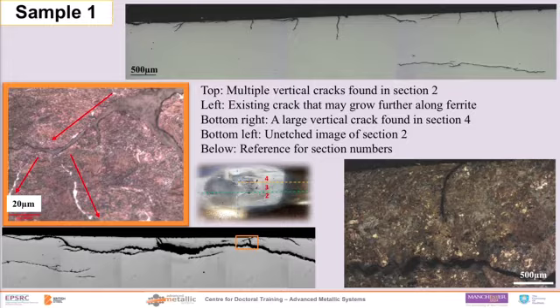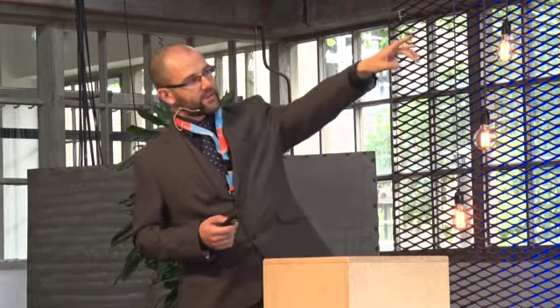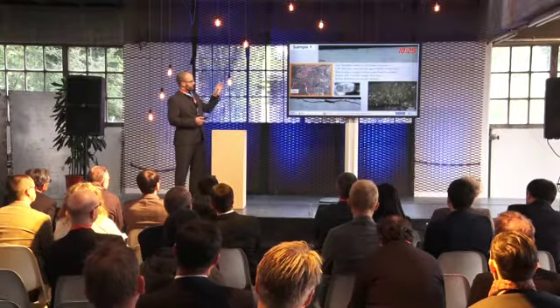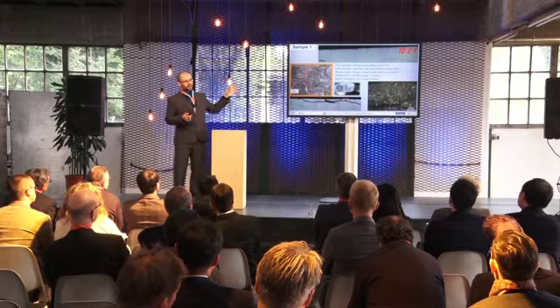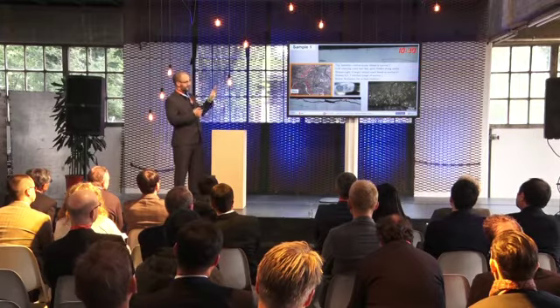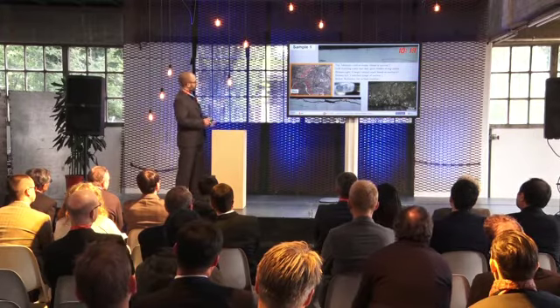You do have some cracks as well which effectively go down a little bit and then resurface quite quickly, and I often found little islands of white etching layer along with these. And you can see there's also an isolated crack down in the bottom right corner, but this could be connected to another crack in a different direction, so it doesn't mean it is isolated as such.